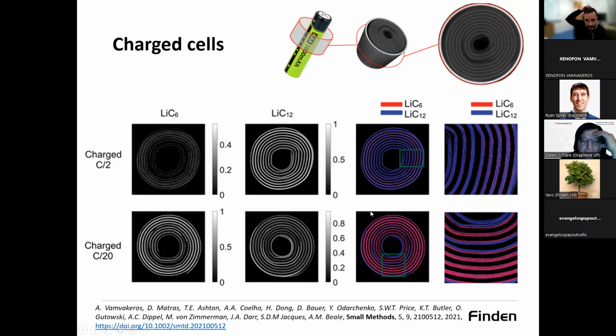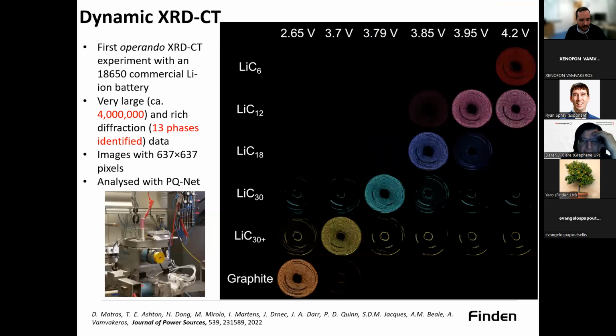So we performed these static measurements first, and then we thought, okay, why don't we try this with a more interesting battery under real operating conditions and see what we get. And indeed, we tried with an 18650, and we published these results in 22. So this was the first operando or in situ XRD-CT experiment of a cylindrical lithium-ion battery.